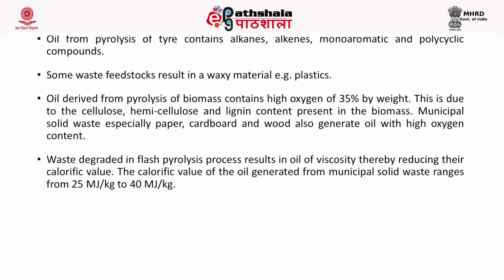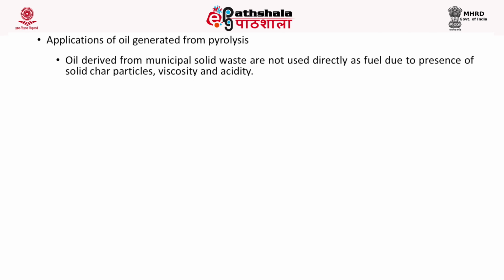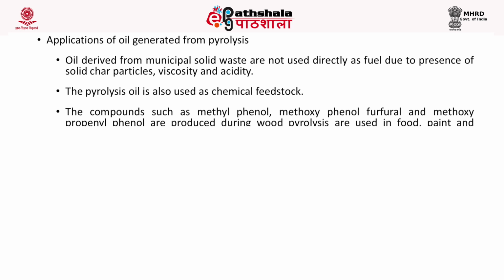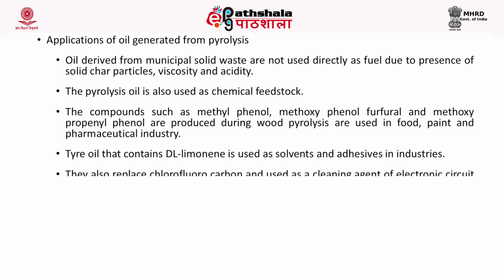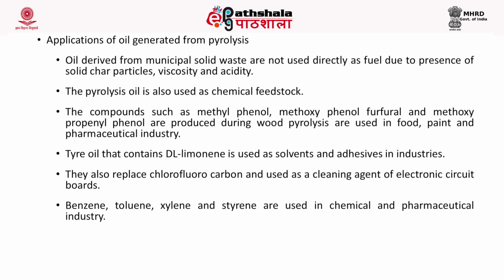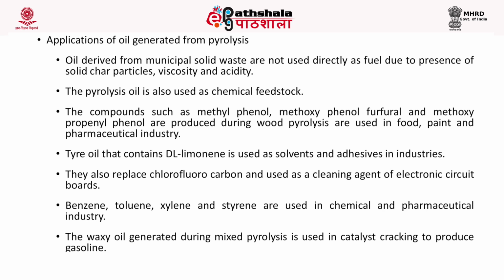Waste degraded in flash pyrolysis might result in an oil of high viscosity, thereby reducing its calorific value. The calorific value of oil generated from municipal solid waste ranges from 25 megajoules per kg to 40 megajoules per kg. The oil generated from the pyrolysis process has a wide range of applications. For example, the oil generated from the municipal solid waste cannot be directly used as a fuel because it contains very small solid char particles. Also, their acidity and viscosity is a little higher.